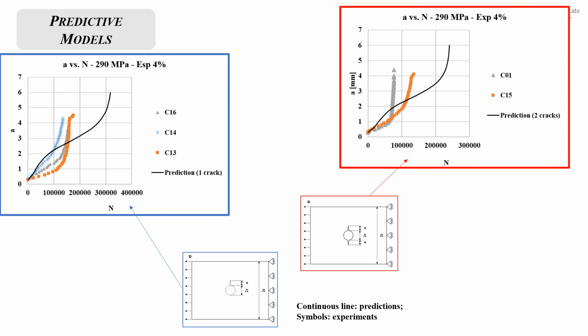For both cases, it is found that the predictive model overestimated the cycles to rupture by a factor of 2, or 8 in the worst case, which is very consistent with the literature. And the higher predicted crack growth rates suggest the probable inadequacy of the models based on the principle of linear elastic fracture mechanics. And, in fact, a first finite element model is under development that is able to contemplate phenomena of diffuse plasticity, which constitute the natural continuation of the analysis carried out in this work.